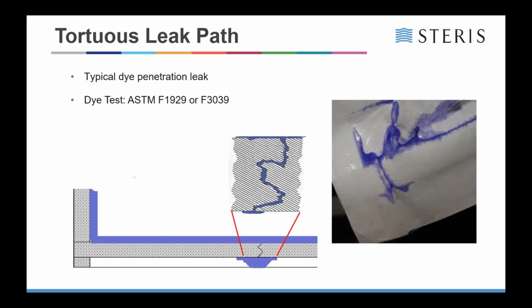Again, looking back at the defect we saw during the visual inspection in the seal, we can see that the dye will run straight through. But one problem is that you can also get false positives, which you need to be very careful of.